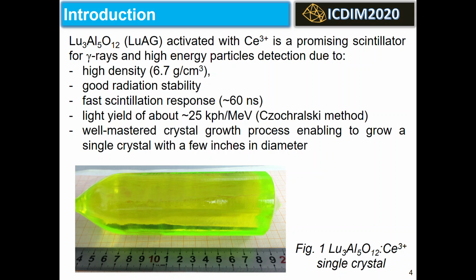LuAG single crystal activated with cerium is a very well known and very well studied material showing promising properties to be used for gamma and high energy particle detection due to high density, good radiation stability, fast scintillation response, light yield of about 25,000 photons per 1 megaelectron volt, and a well-mastered crystal growth process enabling to grow a single crystal a few inches in diameter.